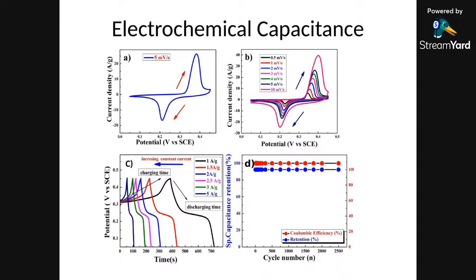Which actually suggests that the behavior is of the intercalative type. And even when we did this galvanostatic charge discharge study, you can see the stable plateau. We are in the aqueous electrolyte, that's why these redox potentials are really low, and for the single cell. So when we have gone for this nickel cell, you can see the discharge and charge potentials are there, and you can get fixed storage.